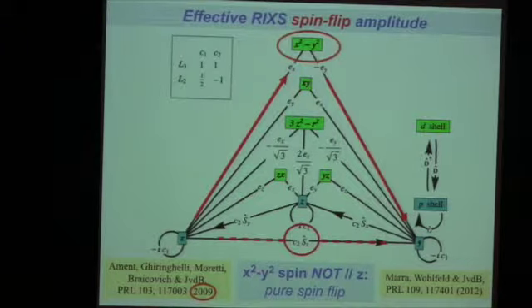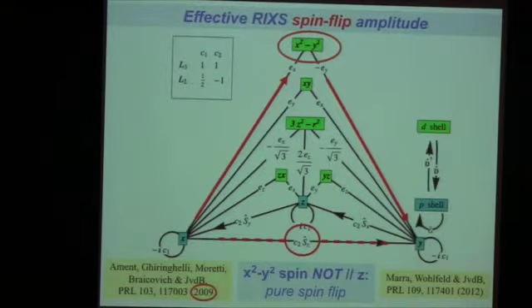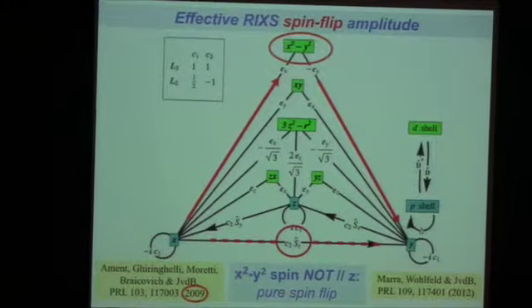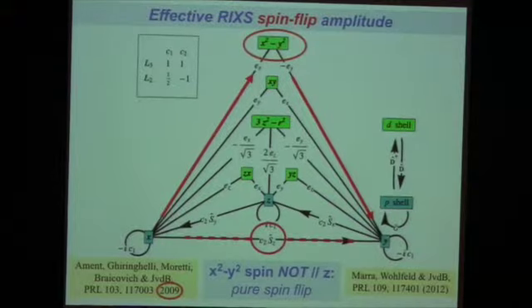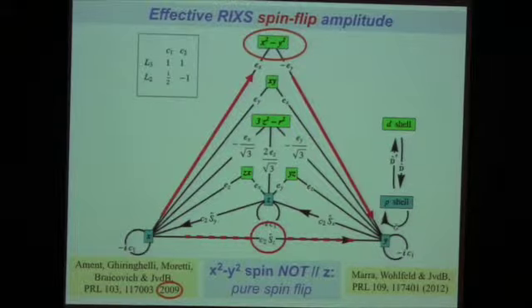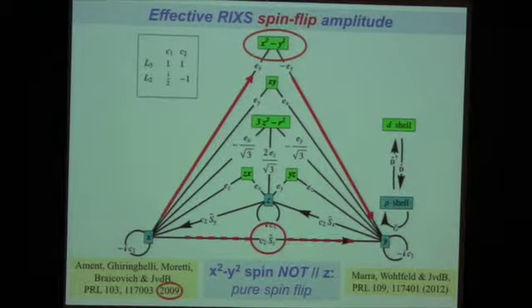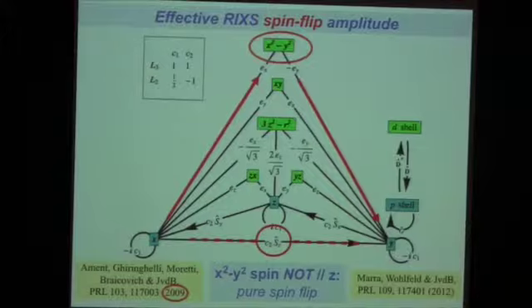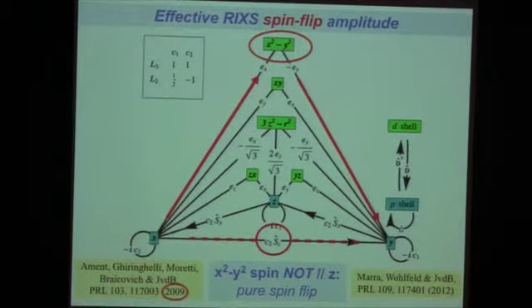So we pointed out that this is possible. In 2009 we pointed out that this is in principle possible, and also that this process is absolutely leading order. The intensity of that should be just as large or comparable to the dd excitation energies. It's leading order because the spin-orbit coupling is huge in the core. Okay. So, in special cases, direct spin-flip scattering is allowed at the copper edge. And now it turns out, we are very lucky, all cuprates are special cases. By special cases, I mean spin in the XY plane.